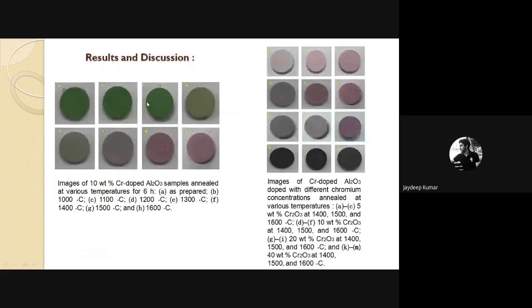So this was the result when the tablets were collected. For 10% by weight of chromium oxide, chromium doped Al2O3, this was the result as soon as it was prepared, and for 1100, for 1200, and so on till 1600. Till here it was green, then gray, then here it was pink. This was the property they wanted to have for further experiments. This was its property, color.